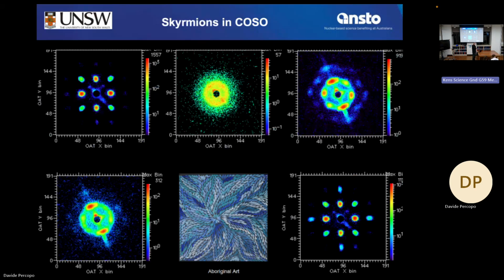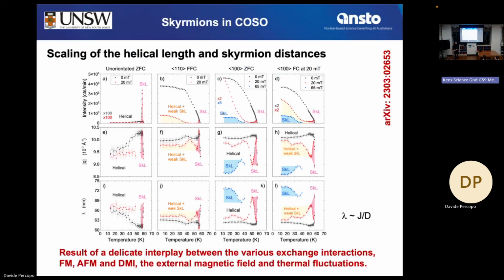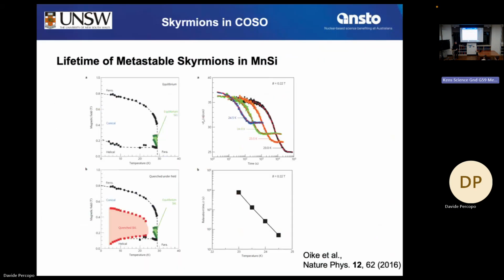Skyrmions, are they relatively stable or do they eventually decay and deform into other things? That's my next paper. Send us the archive link. So the main phase, the skyrmions are supposed to be very stable. Actually, we have new data showing that it's not that stable, but if you quench the crystal, which means you cool it super fast, you can kind of freeze in the skyrmions and they are metastable. So you can generate them by fast cooling.